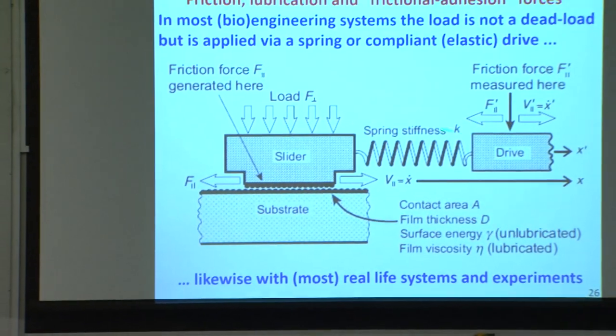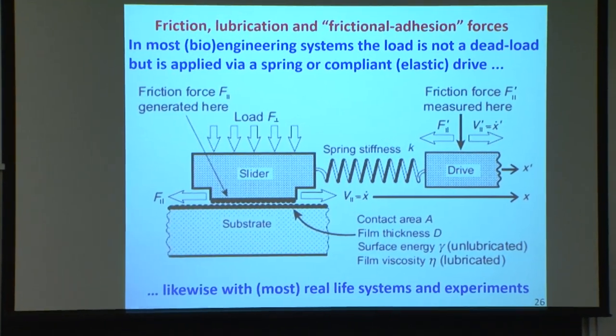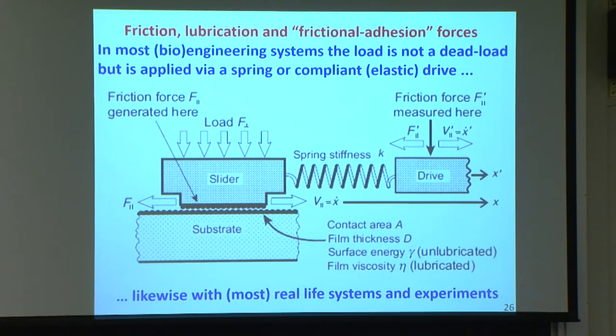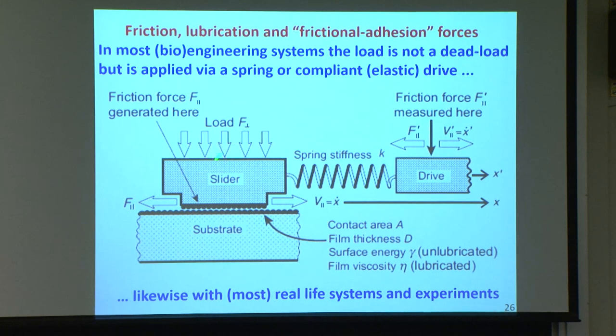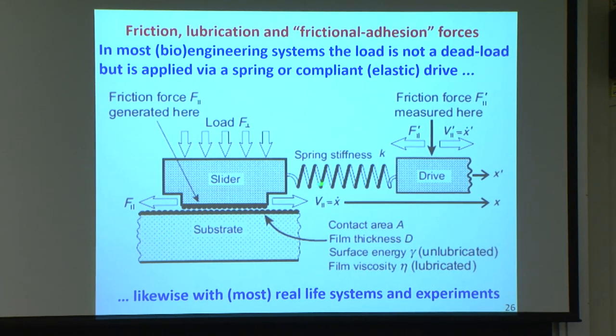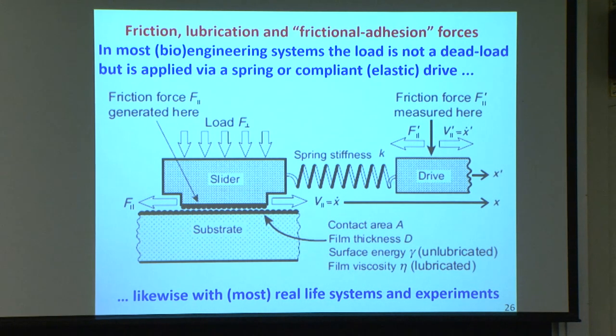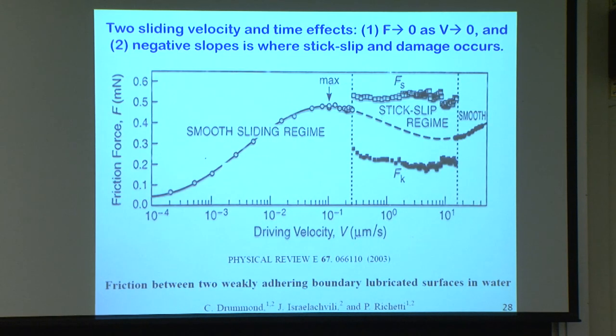Now, to make these measurements is actually quite complicated. Bringing two surfaces together and separating them is pretty straightforward. You bring them together, at a given rate, see how they deform, separate them, keep them for a certain time in contact, and so on. Friction, you have to know how fast you are moving something, then it's connected to the surfaces through some compliant element, and then there's all sorts of complicated things going on. There's a load, there's the viscosity here, which is different from the bulk usually if it's a thin film, and there's the structure of this surface. It's a much more complex process altogether than just bringing surfaces together and separating them. Plus, as you move, as it slides, there can be all sorts of interesting effects going on, as I will elaborate.